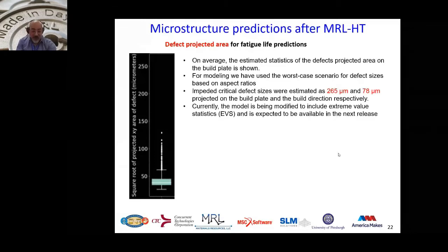And one of the important things: all this was measured on coupon samples extracted from the core of the part at the pre-selected location that we demonstrated earlier to everybody in the first cut of the samples that we did, both the measurements and the prediction.